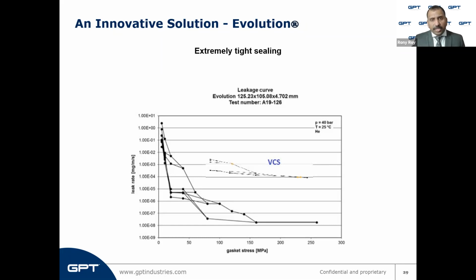If we look at the sealability of Evolution versus a G10 on a stainless steel isolating gasket of the previous technology, you can see that in an EN 13555 leakage test, Evolution has a leak rate of about 1 × 10⁻⁸ helium per second. That's about 1 cc of helium leaked over a 3-year period. Whereas the G10 laminated stainless steel isolating gaskets leak about 1 cc of helium every 3 hours.